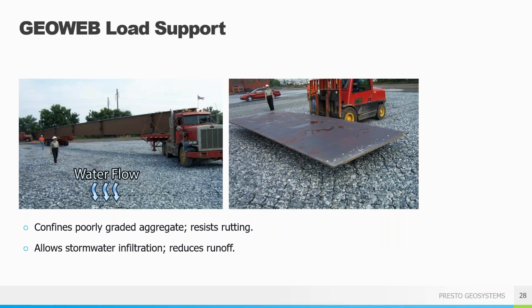Keep in mind, you get infiltration with clean stone only. The permeability of your infill is going to be your limiting factor. Here, an 8-inch GeoWeb and an aggregate with a 40% void space was used. This allowed for about 3 1/4 inches of rainwater to be stored in the pavement section, eliminating the need for additional stormwater infrastructure. You can also see the extremely heavy loads that are able to be handled by the GeoWeb system.